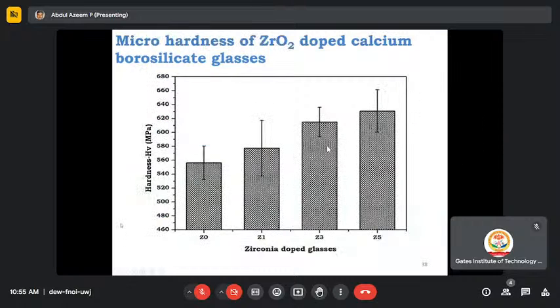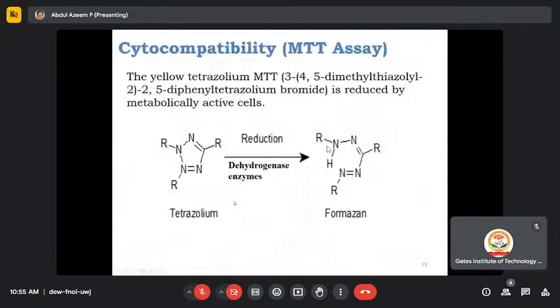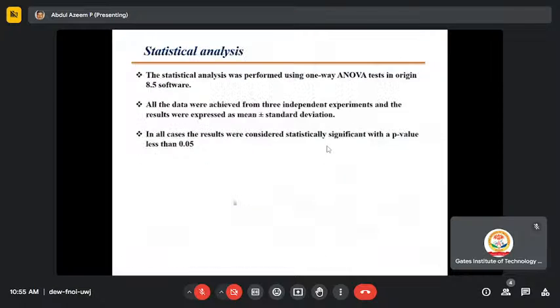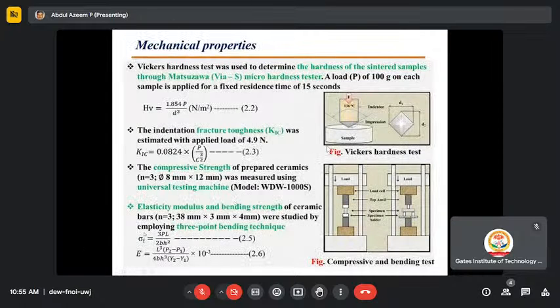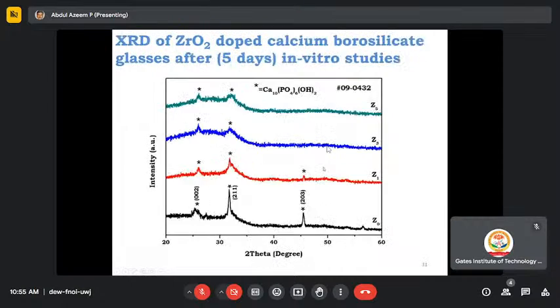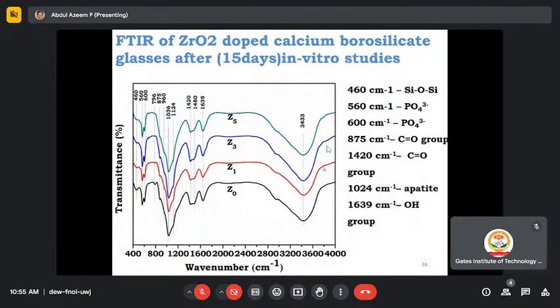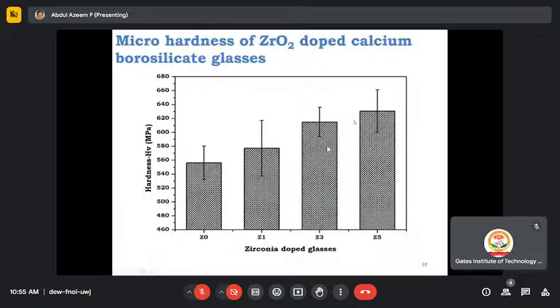Similarly, we have done the hardness test. So see, it is increasing with the zirconium content. We are doing the mechanical studies: compressive strength, fracture toughness, hardness, and so on. So you can observe from this bar graph that with an increase in the zirconium content, the hardness also increases, from 560 megapascal to 630 megapascal.